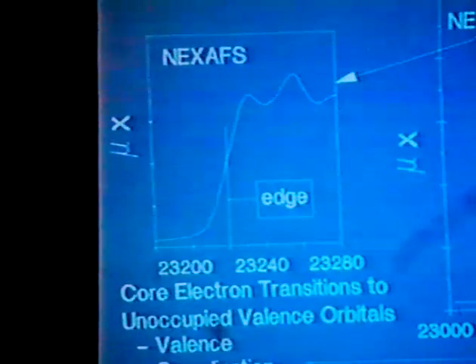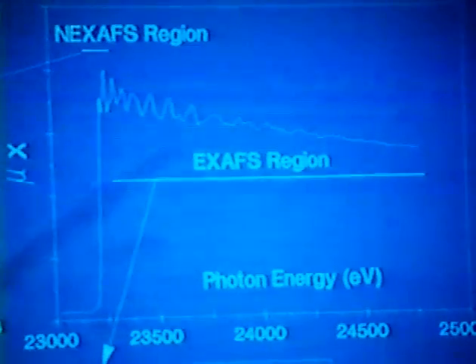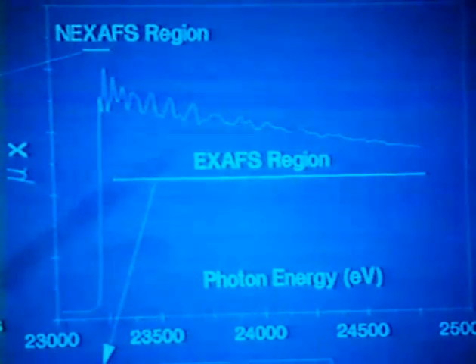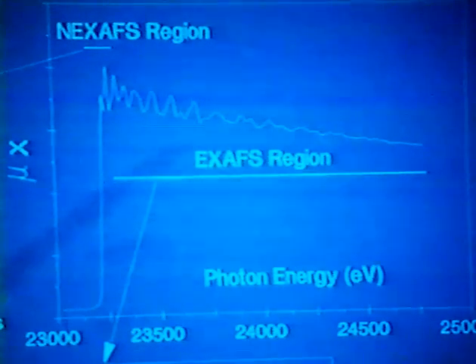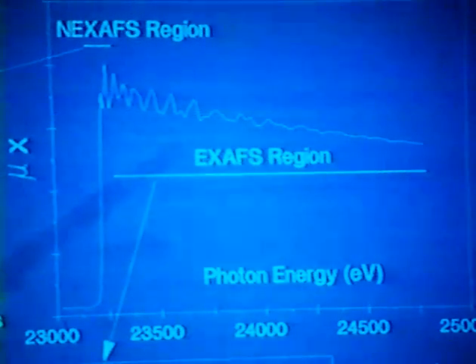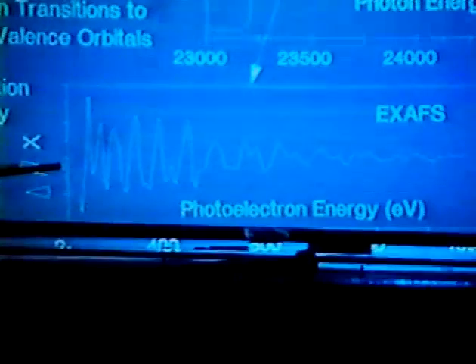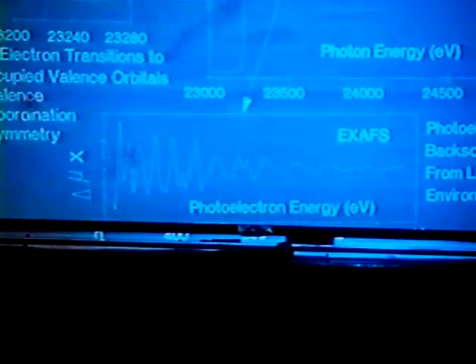But out here, farther out in the spectrum, out to about 2,000 volts frequently, there's some oscillatory behavior. That's the EXAFS, the extended fine structure. And for reasons that are not really evident, if you think about them, what happens is an electron that's ejected from a core hole interacts with the environment of the atom that absorbed the photon in a manner that modulates the absorption coefficient itself. Think about what I'm saying. It's saying that the electron has absorbed a photon, it's gone out and interacted with the environment and modulated its own absorption coefficient. And it's quantum mechanical.